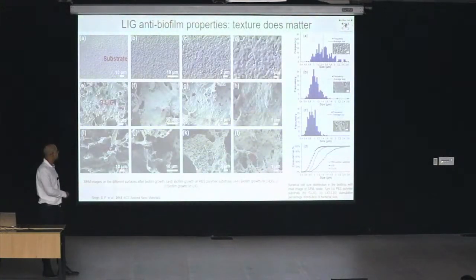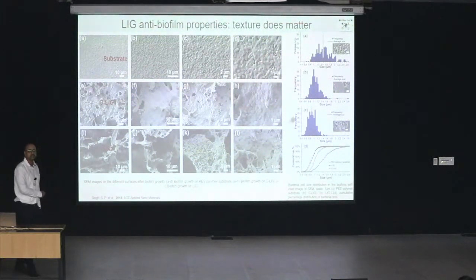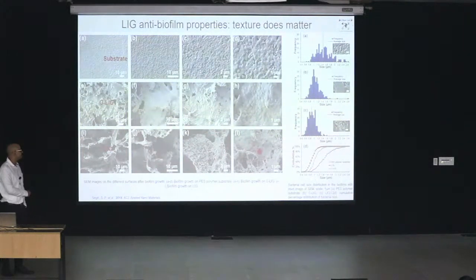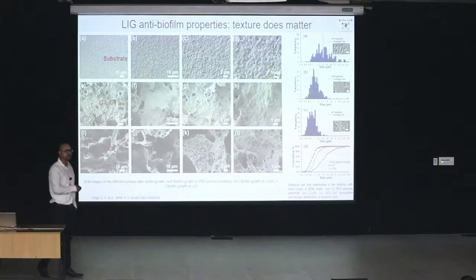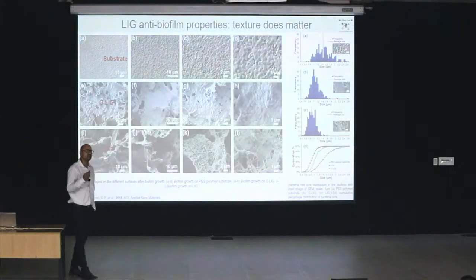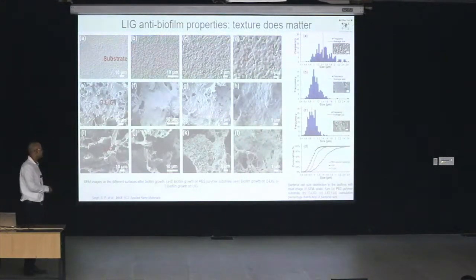Also, one interesting thing we have found: when we started the experiment with these microorganisms, generally we did the experiment with Pseudomonas aeruginosa, which is a rod-shaped bacteria, and their size was around 1.5 micrometer. But later on, some of the microorganisms that got attached to the graphene surfaces, you can see, converted to a cocci or a circular shape. So we have seen with this laser-induced graphene, when the microorganism was trying to attach to the surface, they were not able to easily attach, so they tried to change their shape to attach to these surfaces.